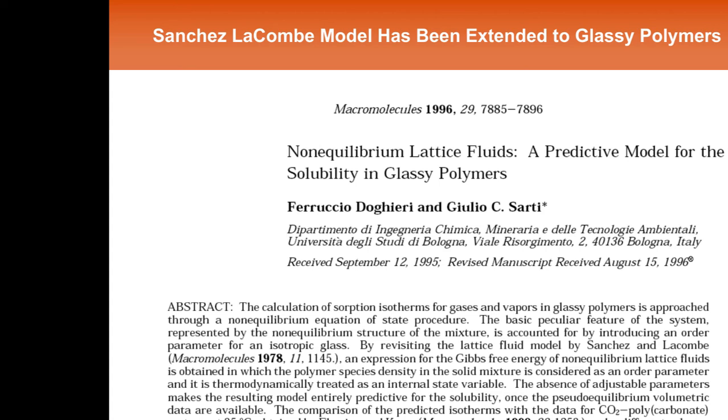A value of 0 would mean that the methane doesn't swell the polymer at all. Butane is even more extreme. You don't see any swelling until you put almost 20 cc's per cc of butane in the material, and then finally it begrudgingly starts to swell a little bit. But this material is unusual in the sense it has a very, very high value of this non-equilibrium excess volume. As a result, you see that not only in the solubility properties, I'll show you later, you see it in the transport properties, and you see it in things like these dilational or volumetric properties.